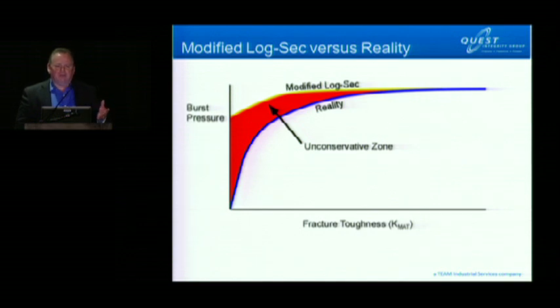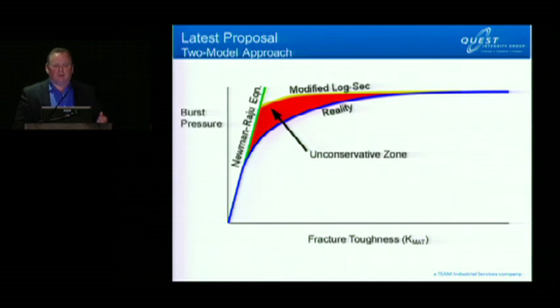As a real-world example, this morning the Mayflower, Arkansas incident was mentioned. If you use modified log secant on that particular incident, you predict that it didn't happen, because it way over-predicts the failure pressure. Now, more recently, in some of the PHMSA-sponsored research, there's a new proposal that said, okay, we recognize it doesn't work at low toughness, so we'll introduce another model for linear elastic, and that's based on some work that was done at NASA in 1980, and it actually applies to a flat plate, not a pipe. But let's be generous for a moment and assume that it gets the linear elastic part correctly.